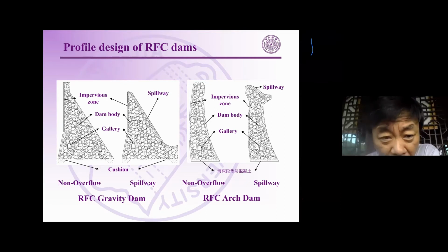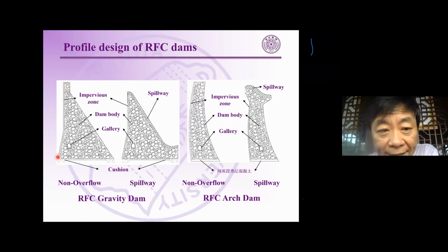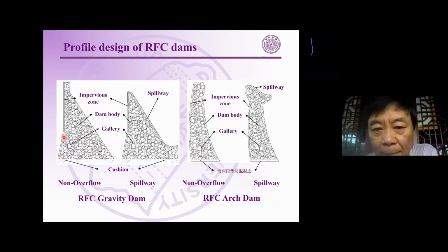This is the zoning of a gravity dam or arch dam built with rock-fill concrete. We can see that usually at the upstream, we set an impervious zone. Usually the thickness is 300 millimeters to 600 millimeters, or usually half a meter. This impervious zone is built only by self-compacting concrete. It means it is without any rocks in this zone.